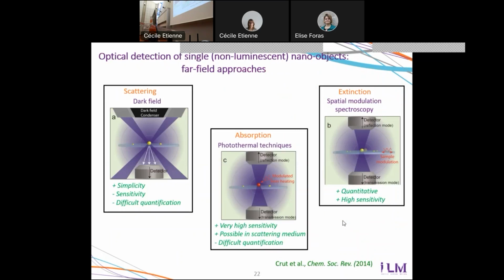Several tools have been developed. For instance, dark field microscopy is a tool that selectively detects the scattering by single nano-objects. It's a simple tool, but hard to use for quantitative studies. Also, photothermal techniques use the absorption by single nano-objects. The idea is that once a nano-object has absorbed light, its refractive index and that of its close environment will not be the same as previously, and this will change the path of a second beam. It's a very sensitive method, however, more complicated than the first one because it requires two different light beams.